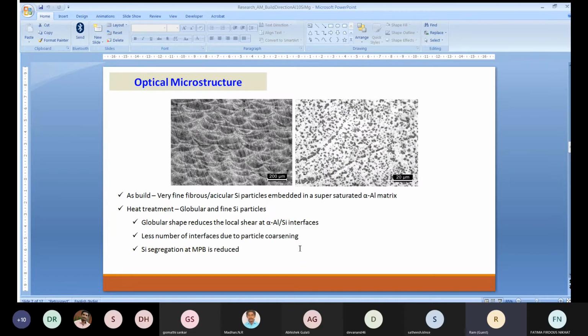These are the optical microscope pictures. Left side is as-built, right side is after T6 heat treatment. The observation is that in the as-built condition, you can see clearly the laser tracks, which have very fine fibrous or acicular silicon particles embedded in the supersaturated aluminum matrix. And on the right side you have globular silicon particles of fine size.